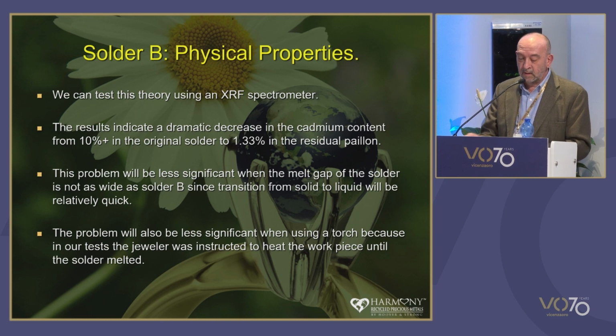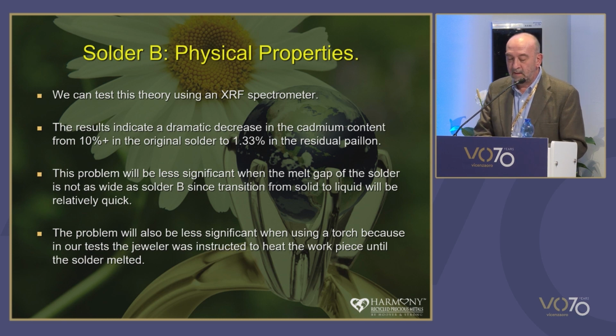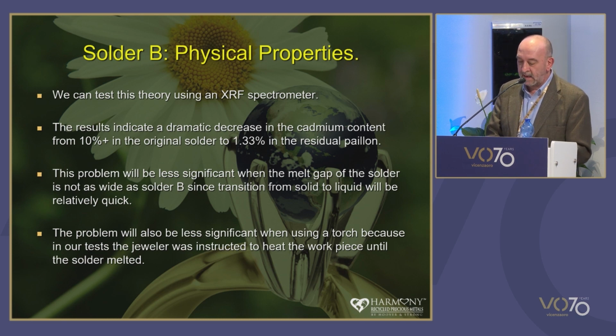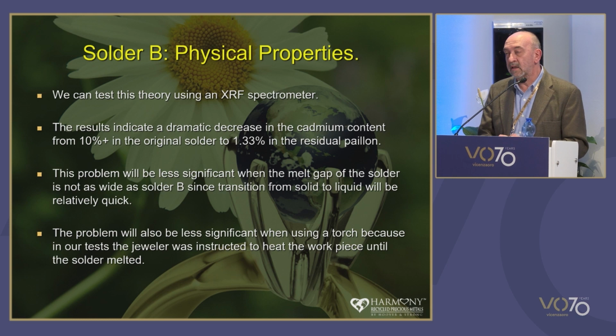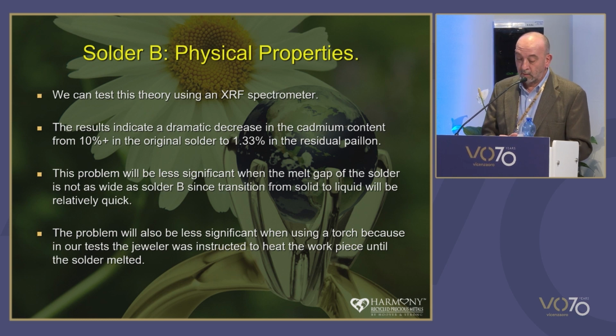So what else did it show us? Well, it indicates that if the liquidus of an alloy is lower than the solidus of the alloy to be joined, and the melt gap is sufficiently narrow, and provided the chemical requirements for wetting are fulfilled, any alloy should successfully join any other alloy.